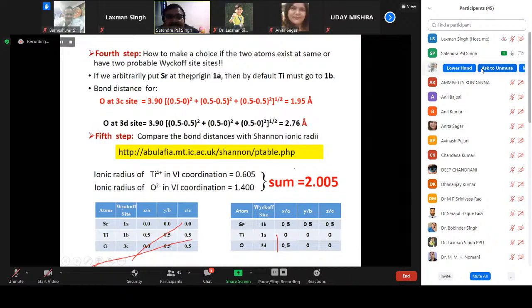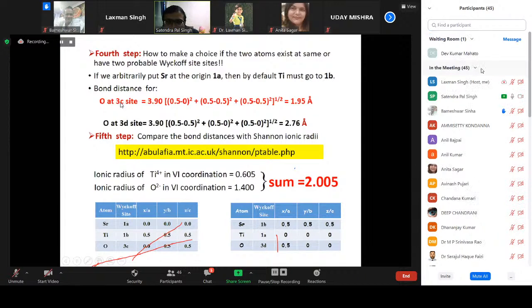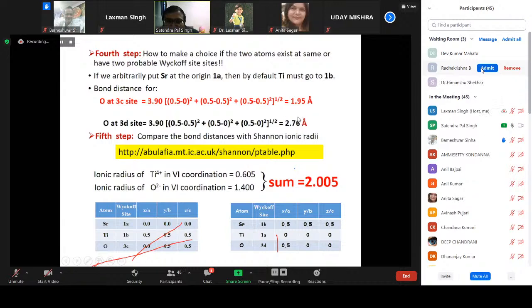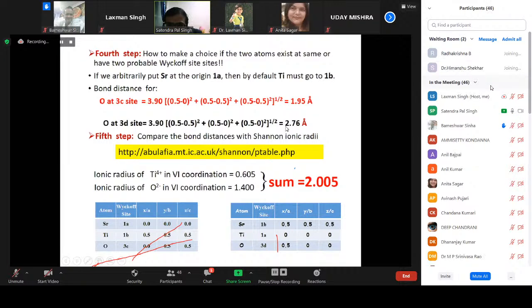Okay, so the 4th step is to denote the sites. Now, if you put strontium at the 1a site, then by default the titanium must go to the 1b site. In that case, we have to measure the bond length by putting the oxygen at the 3c site and the 3d site. If you put it at 3c, the bond length will be 1.95 angstrom. If you put it at 3d, the bond length will be 2.756 angstrom.